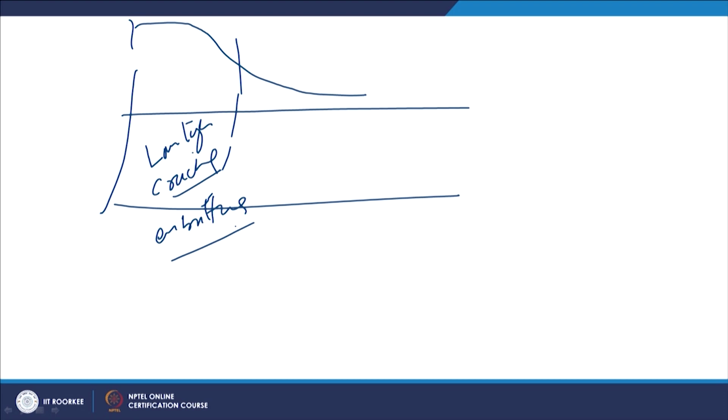This is the typical feature of transformation hardening steels, where high cooling rates lead to increased embrittlement, loss of toughness, and high hardness.